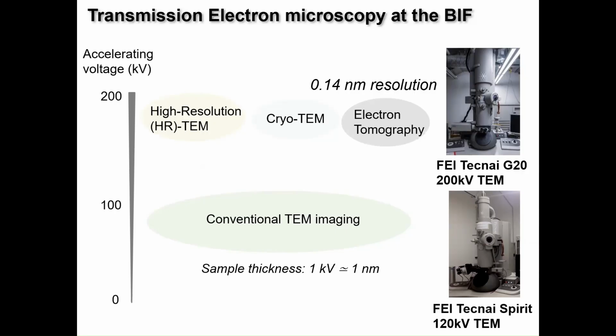For conventional TEM imaging, we use around 80 to 120 kV accelerating voltage, and usually we calculate sample thickness 1 nanometer per 1 kV electron beam. So if we are making sections for conventional TEM, we usually make 70 to 100 nanometer thickness sections. And if we increase the accelerating voltage, then we get higher resolution image.